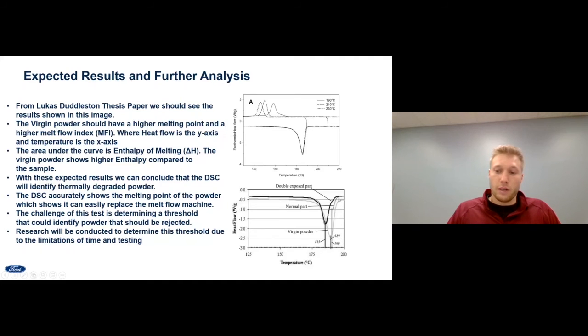Also, looking at the graph, this area under the curve right here is our enthalpy of melting. As you can see with the virgin powder, we're expected to have a higher enthalpy of melting. It has not been thermally degraded yet, so its structure is stronger. So with these results, we conclude that the DSC will identify thermally degraded powder. The DSC accurately shows the melting point, which is important because this proves that we can replace the melt flow machine.